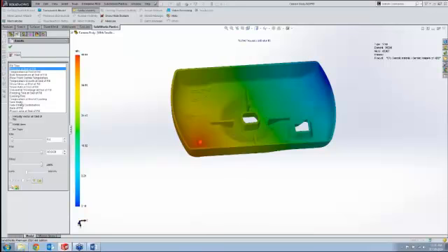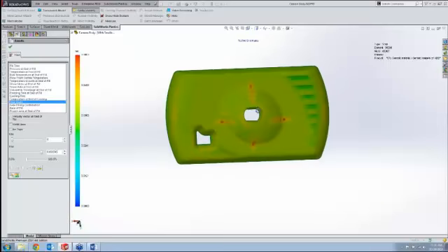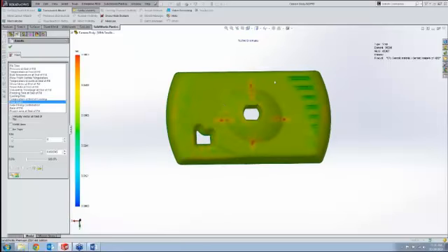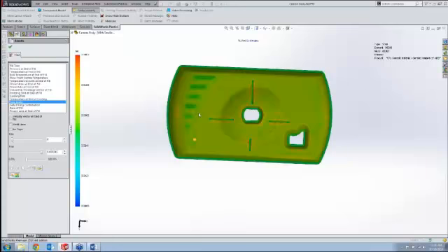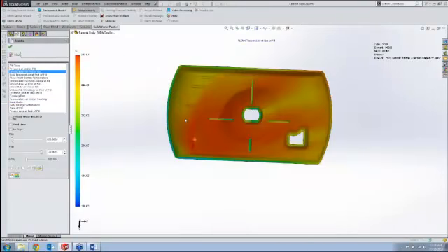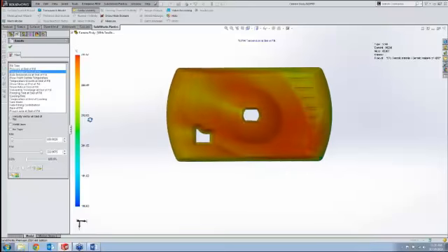And then taking a look at the sink mark analysis on this side, you can see I've got a much more uniform displacement in the sink mark analysis here. I've still got potential marks going to happen here, but I'm more uniform across the board on all of these colors, which is going to give me a more uniform cooling effectively, which you can also see in the temperature at end of fill. A lot more uniform across the part.